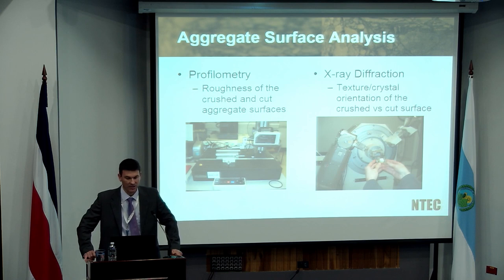The other approach is to look at X-ray diffraction. If we are interested to make sure that the crystalline structure or the crystal orientation of our minerals in our aggregate were effectively exactly the same as what you'd find in a normal crushed aggregate, we would have to do some kind of X-ray diffraction. And again, this was done because there's always a concern when you produce a laboratory test that you may potentially be artificially changing reality in terms of how the materials perform when they're in an asphalt mixture.